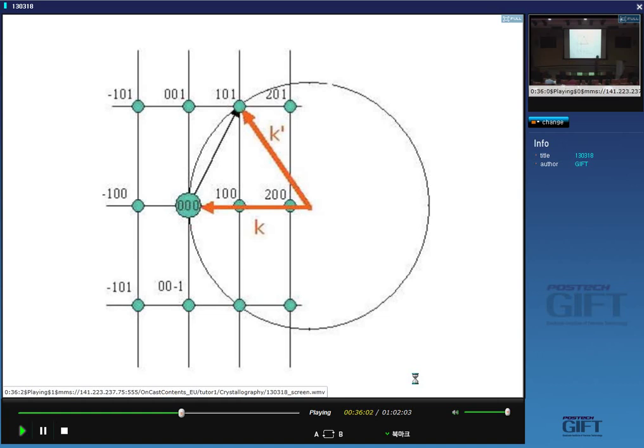Now, in this diagram, we've got the incident beam coming along a particular direction, and the crystal is fixed. But often you do diffraction experiments where you rotate the crystal, right? You put it into your X-ray diffractometer, and the specimen is going round and round. So all you have to do is rotate the reciprocal lattice itself, and every time one of these points intersects the sphere, you will get a diffracted beam. So you can represent all kinds of diffraction experiments by taking the Ewald sphere and superimposing it onto a reciprocal lattice.